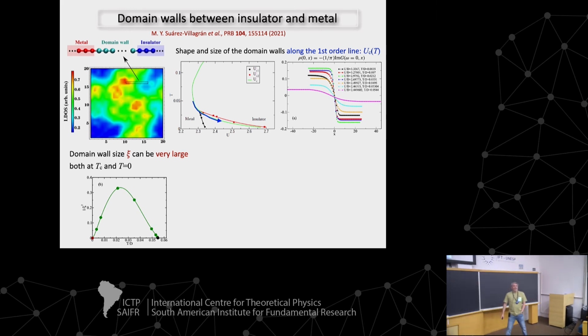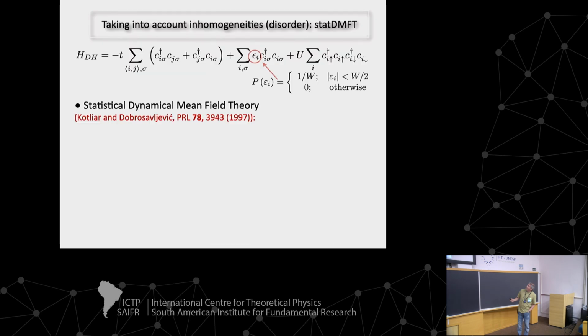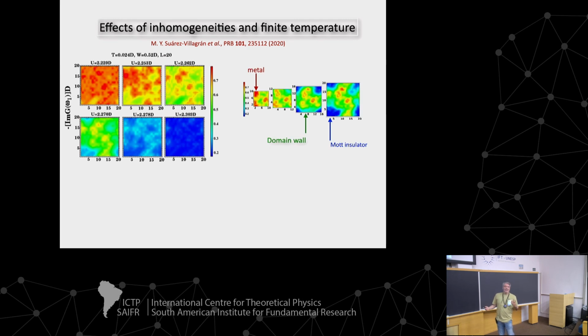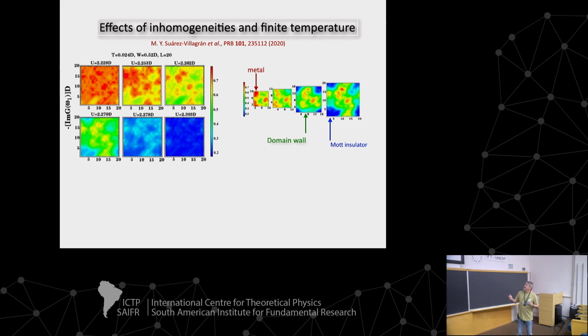Absolutely, absolutely. For instance, you can understand this data just like dynamical mean field theory is an Ising model, basically. It's a fancy Ising model. If you put the disorder that I put, this is the random field Ising model, which in 2 dimensions has no transitions, Imry and Ma. And this is consistent with what we see up to the lengths we can go.